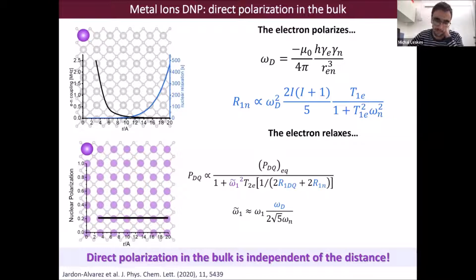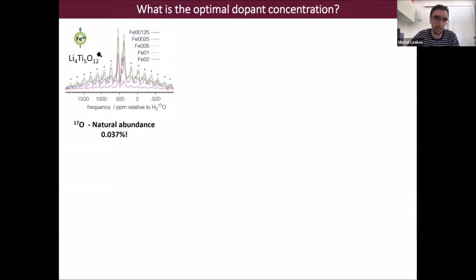So let me look at another example of a sample that we measured. In this case, we looked at lithium titanium oxide, which is a material that can be used as anode in lithium-ion batteries. And we doped the sample with different amounts of iron 3+, which is paramagnetic in nature. And with this, we were able to get oxygen-17 natural abundance spectra in just a few scans. So a question that we were asking ourselves is, what would be an optimum concentration of metal ions for DNP purposes?